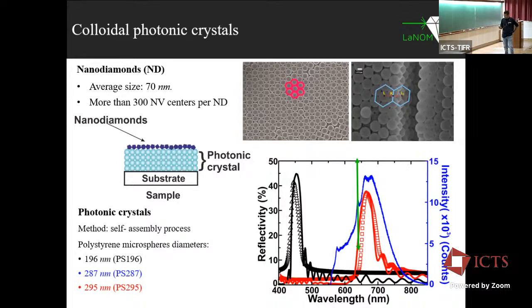of the NV center. You can see that we made a photonic crystal which has a band gap around 450 nanometer, which is a reference sample because the NV center emission is from 600 to 750 nanometer, and this does not have any effect there. And this sample, which we call the red color sample, is our main sample, where the band gap matches the NV center emission properties.